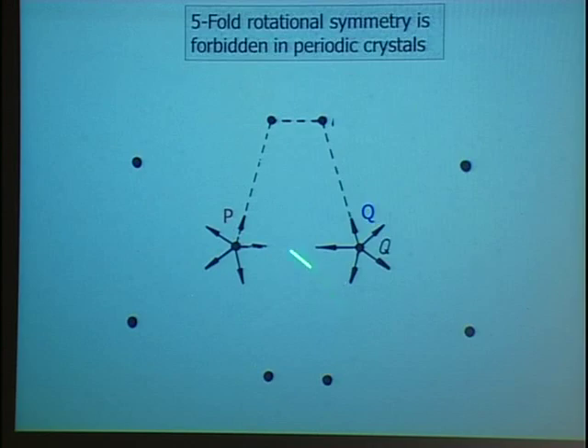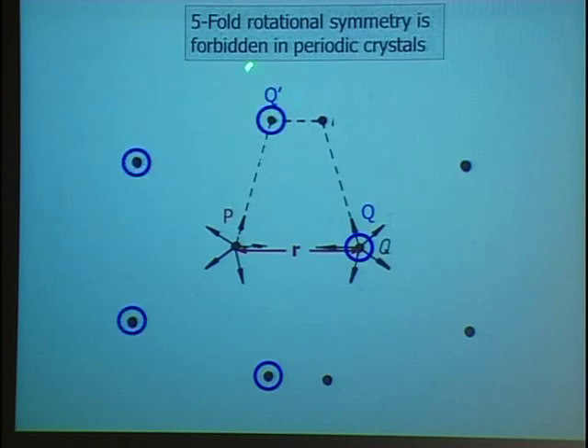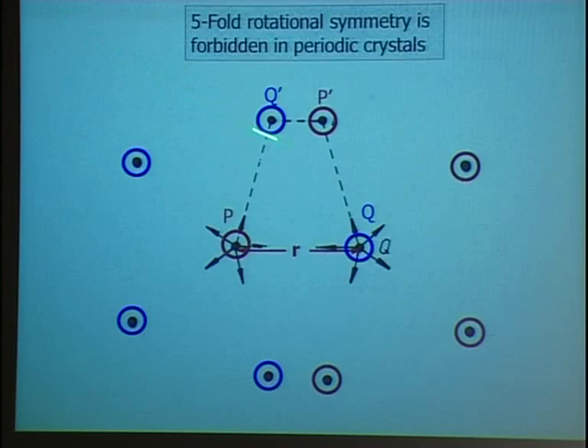In order to do that, let's take two atoms, P and Q, and choose two atoms which are closest together. So the distance R is the shortest distance between two atoms in that lattice. And now, if five-fold rotational symmetry is allowed, then we can rotate Q around P five times, and P around Q five times, and let's see what happens when we do that. So here's Q, 1, 2, 3, 4, and 5, and there should be a Q prime atom here if five-fold rotation symmetry is allowed. Let's do it to P, 1, 2, 3, 4, 5, and there should be a P prime atom here. But because of geometrical reasons, the distance Q prime, P prime is shorter than between Q and P here, and this is impossible because we chose the shortest distance between two atoms. Okay. No five-fold rotational symmetry.